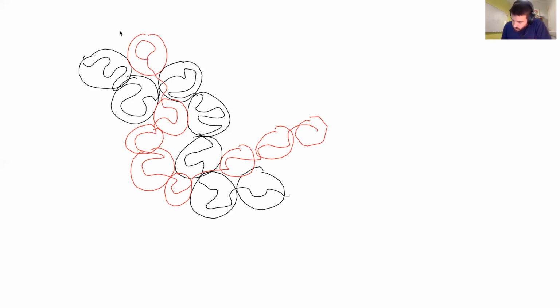Inside each blob, you have solvent everywhere. Same for any of those. And so I can pave the full space with those renormalized chains. But what is interesting is that by tuning the volume fraction, if I increase the volume fraction, I will simply reduce the amount of solvent and reduce the size psi progressively. So psi will reduce. And at some point, I will end up with a pure melt, with psi being equal to the monomer size.